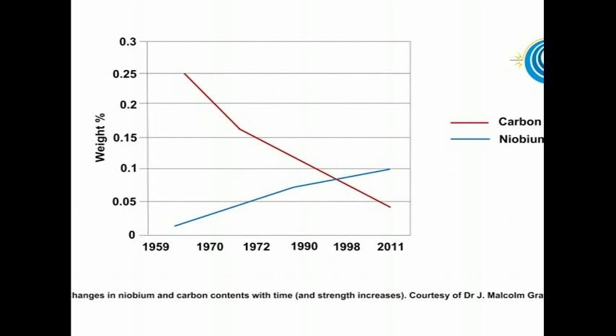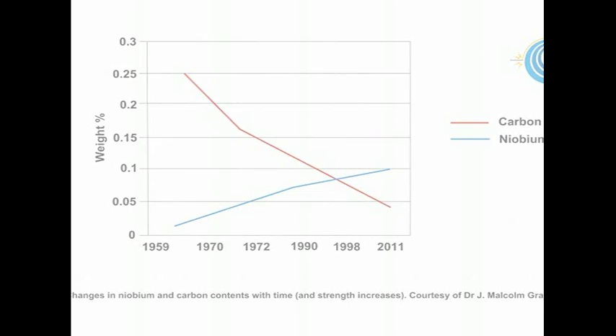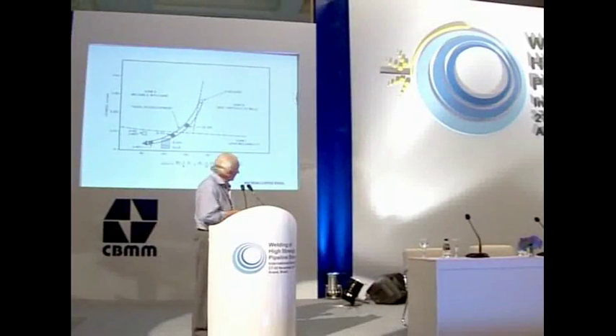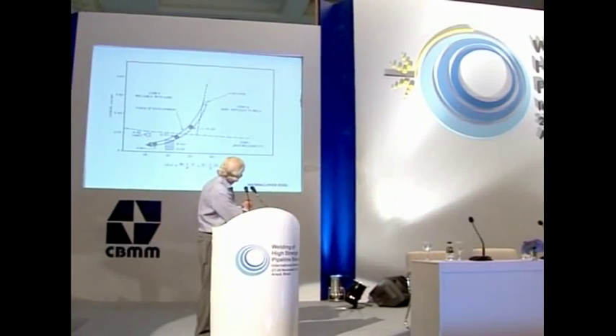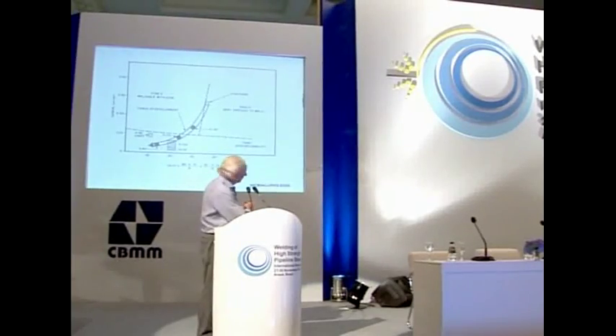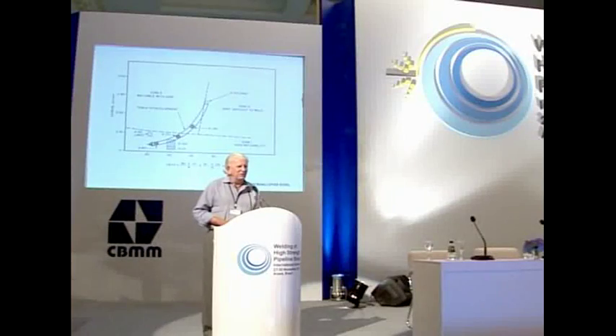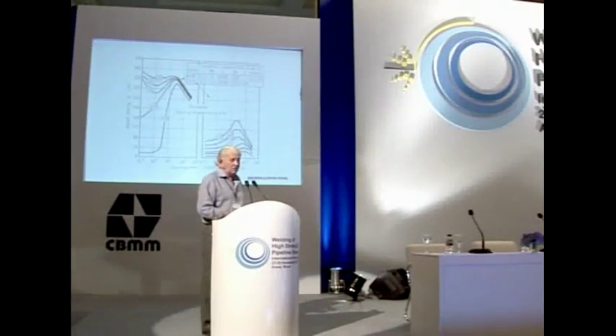But in the intervening years, advances in oxygen steelmaking, plate rolling mills, and our metallurgical understanding mean that it is now possible to produce X80 grade material at carbon levels below 0.05%. Such low carbon levels, combined with advanced higher temperature rolling schedules, allow the effective utilization of much higher levels of niobium, typically around 0.1%. Such steels are commonly referred to as HTP. Dr. Gray observed that millions of kilometers of niobium-containing line pipe steel have now been successfully installed worldwide.